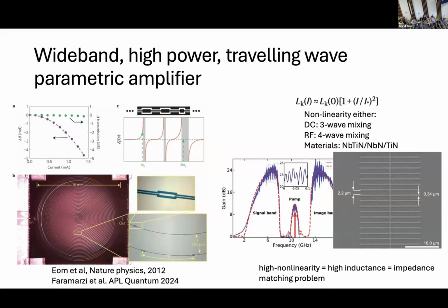One is to put a DC current on the line to create most of your nonlinearity and then put the signal that you want to amplify on top of that. It's called three-wave mixing, for reasons we won't need to go into. Or you do it with a strong RF pump, a microwave pump, from which you draw the power to amplify the signal. This is a random example that I took from the literature, and it shows that this can be a very wide band amplifier. Typically you can amplify over an octave of bandwidth, a factor of 2, which you can shift around by choosing different parameters or a different pump tone. Because they are traveling waves, they don't resonate, so in principle you can shift your pump tone around and get amplification in a different band.